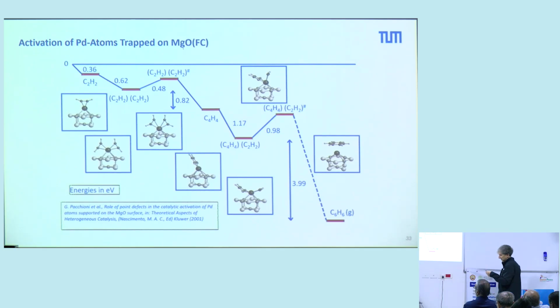And this is the reaction path, also quite old results. And you see here that the rate determining step is indeed the formation of benzene. But you have to charge the cluster. That means you have to adsorb it on an electron donating site. This is an F center. Or you can produce very thin films so that you have a charge transfer from the underlying support material.